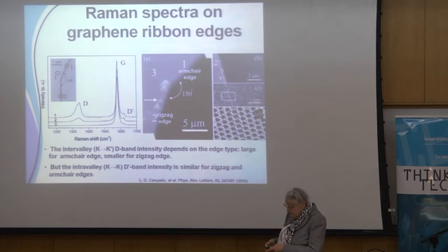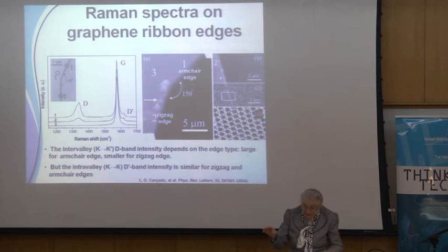For example, the D band, that's a disorder-induced band, for an armchair and a zigzag, because of the matrix elements, this has to do with quantum mechanics, have very different sizes, so that the scattering intensity is very different. The bottom line is you can distinguish them very easily spectroscopically. So we know which kind of ribbon we have. We don't have to touch it or anything. We just shine light on it, and we know the answer.